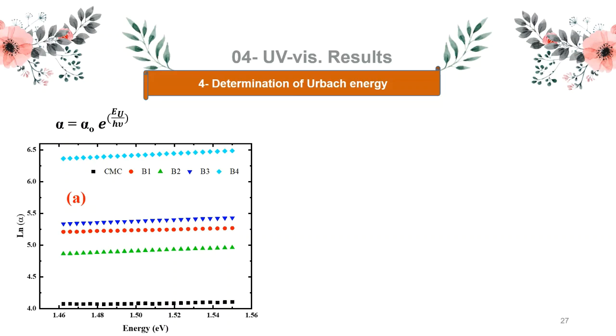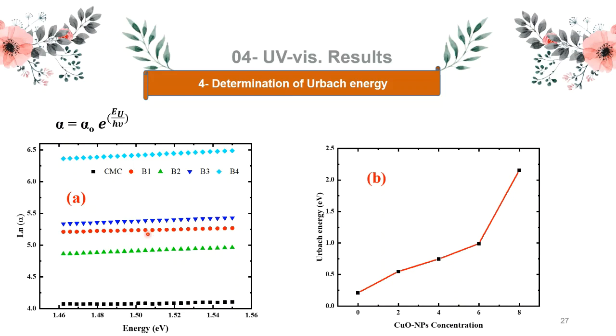This figure presents the linear relationship between the values of ln alpha and the photon energy for the pure CMC and CMC doped with different concentrations of copper oxide nanoparticles. It can be seen from the figure that increasing the photon energy results in increasing the value of ln alpha. The relation between Urbach energy and copper oxide nanoparticle concentration was presented in this figure, and it can be seen that the Urbach energy increases with increasing copper oxide concentration, which means that the number of localized states within the forbidden gap increases, and hence facilitates the electronic transition within the forbidden gap.